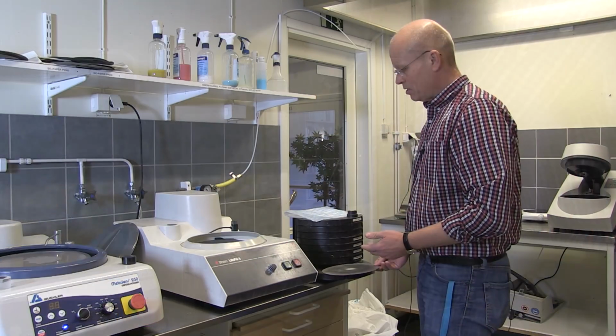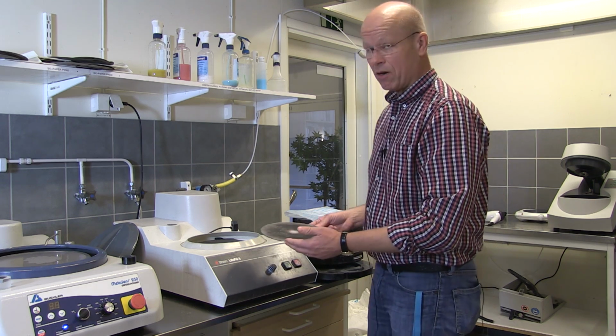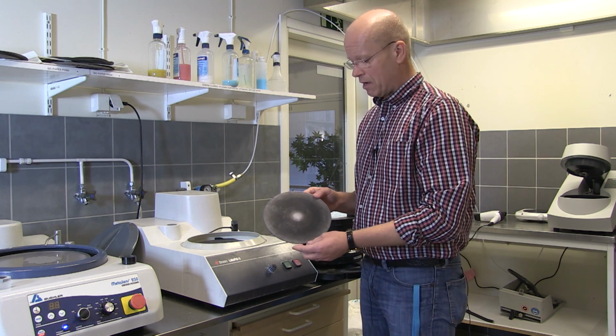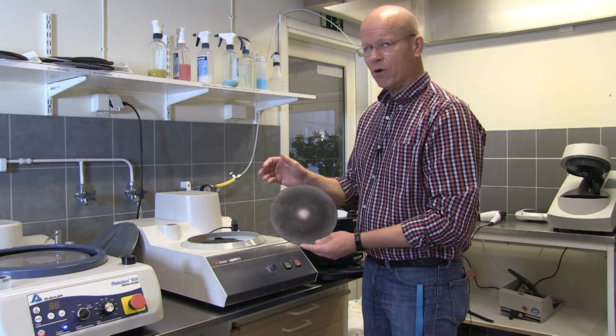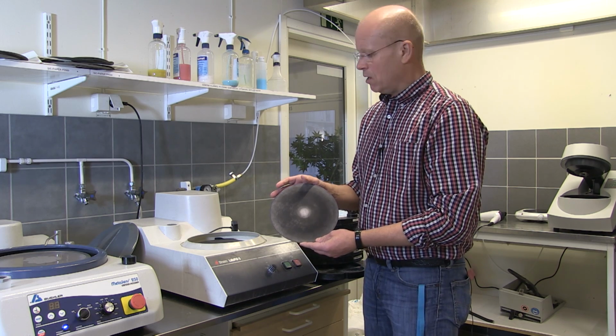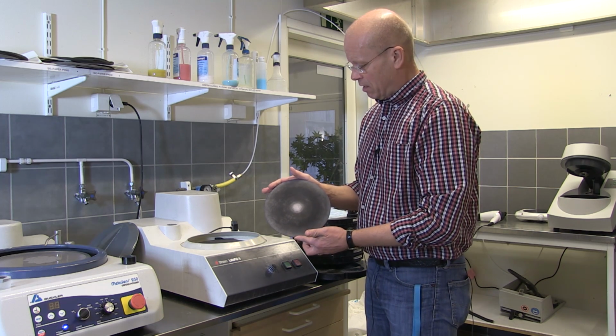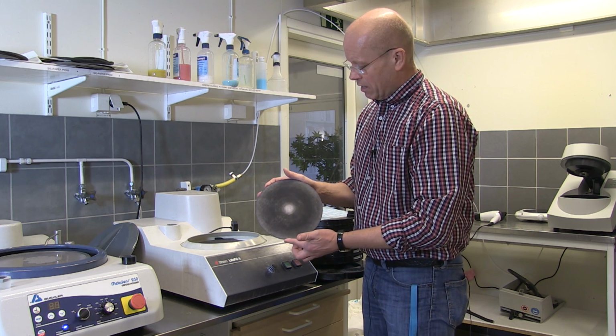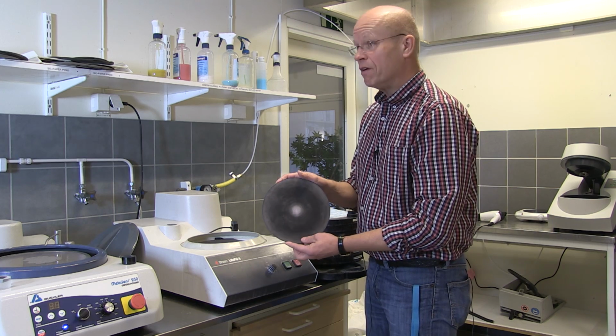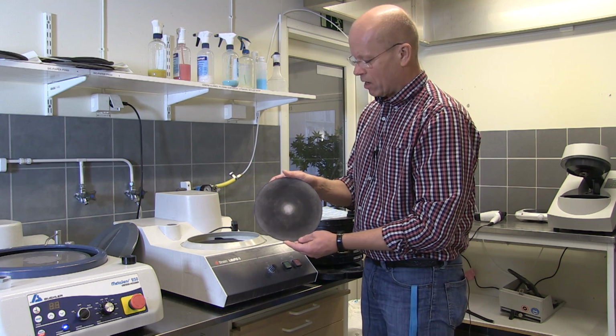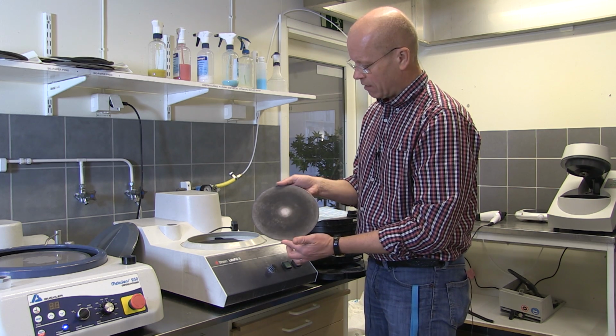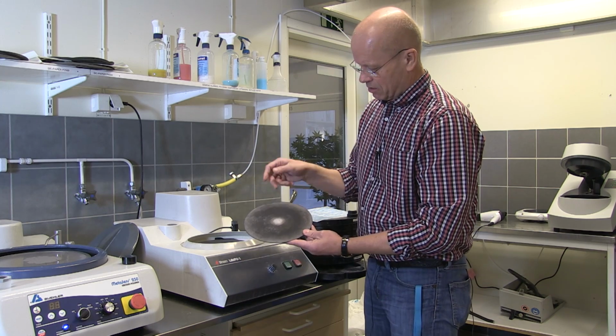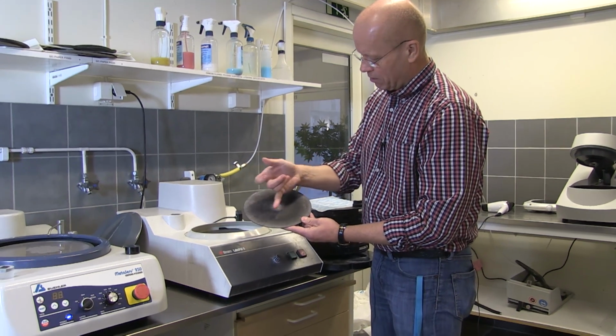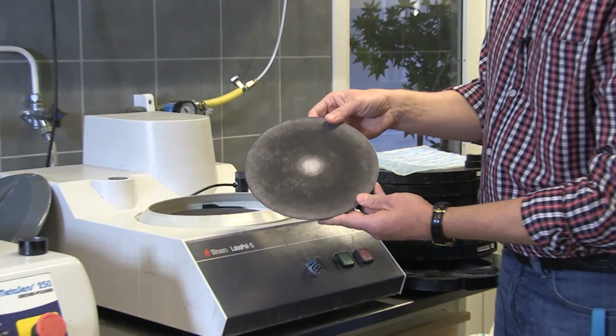The first polishing step will be with 9-micron diamonds. And I think I have not mentioned diamonds yet. We worked with silicon carbide before, and now we work with diamonds instead. So 9 is coming after the 15-micron step on grinding paper. The cloth looks like that. It's a little bit of white in the middle, otherwise it looks quite dirty there.